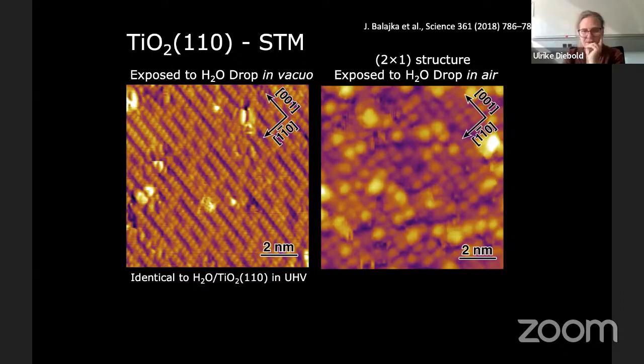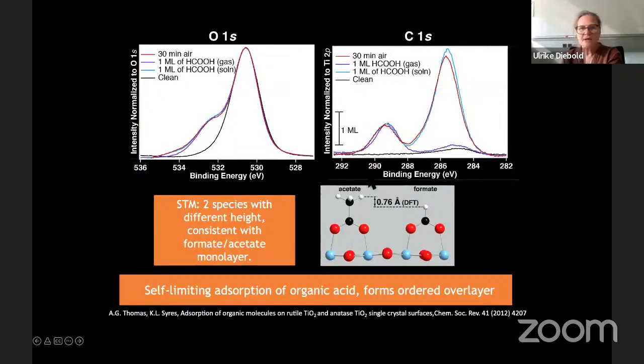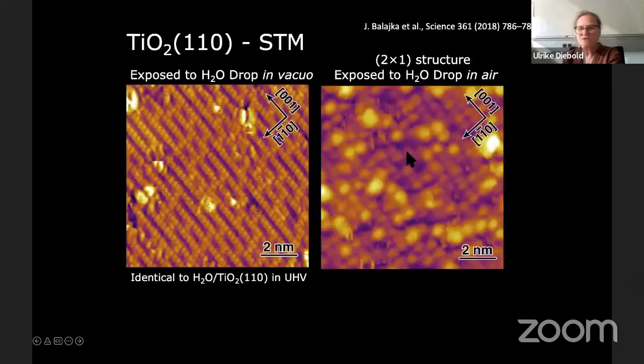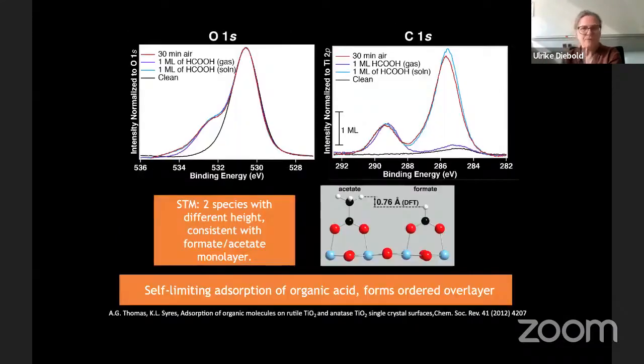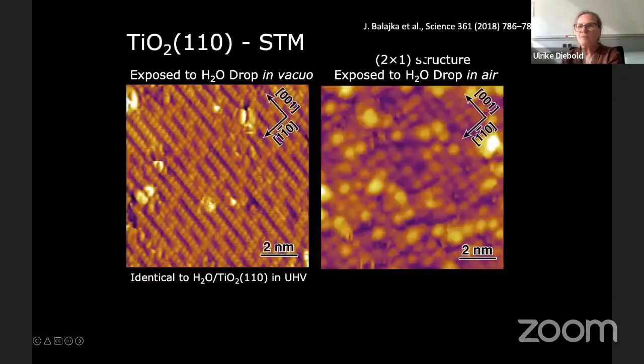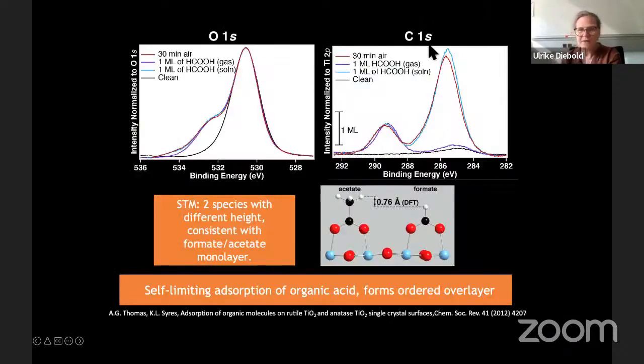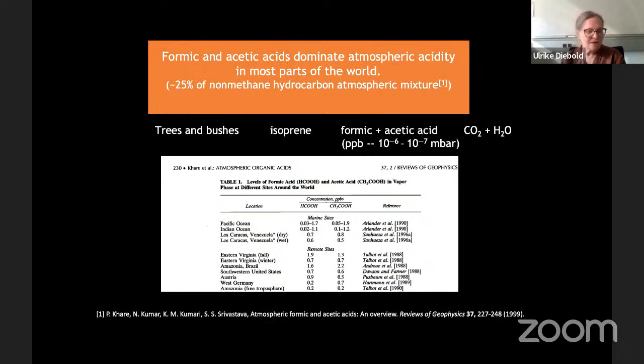We know when you do it outside of vacuum, what you get, this 2x1 overlayer, essentially. This is XPS. We know that then you get quite a bit, up to 1 monolayer of some acetic acid on the surface. So we think that what you have here is actually dirt that comes from the air. And in this paper, we speculate quite a bit about where it comes from. I will not go into the details, but suffice it to say, if you do things not in the ultra-high vacuum chamber, then things are invariably dirty. Okay, that's what I can tell you.